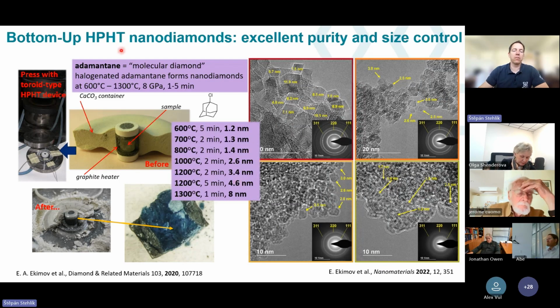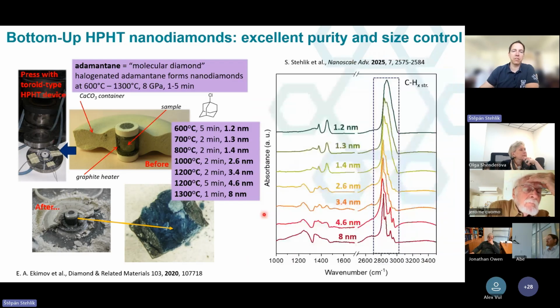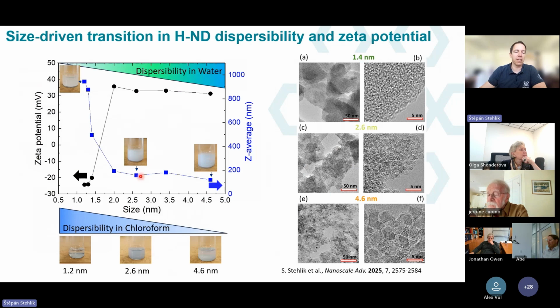What is very nice about this technique is that we can control the size of the nanodiamonds just by the parameters and especially by the synthesis temperature. With increasing temperature, we can increase the size of the nanodiamonds, and these particles are really quite monodisperse, so they are perfect for these size-dependent studies. What is also very special is that from the synthesis, you can see on FTIR spectra that they are perfectly hydrogen terminated. So here we don't need to do any ex-post hydrogenation, because these particles from the synthesis have a perfect hydrogen termination.